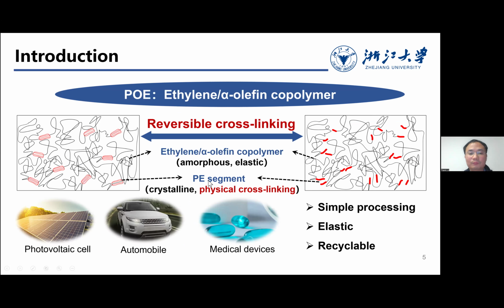And they also have segments with no content of alpha olefins, which means they can crystallize and form physical cross-linking. In this way, the physical cross-linking binds these chains together and forms a good elastomer. Because of this, they can be widely applied in different fields. For example, you can use them as encapsulation materials for photovoltaic cells, an area that is increasing dramatically. You can also use them in automobiles, especially new energy automobiles, and in medical devices. All this is because they are processed very simply, they are elastic, and more importantly, they are recyclable.